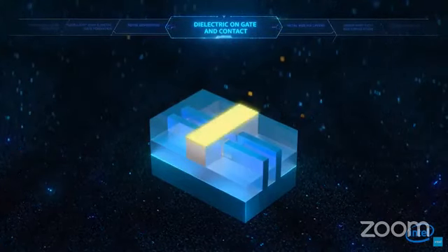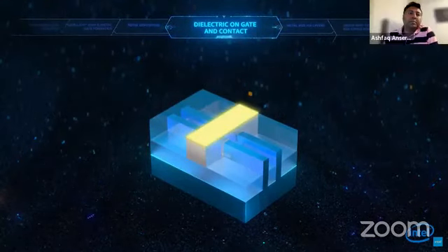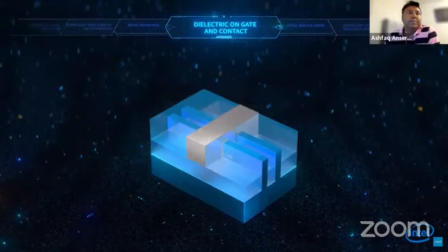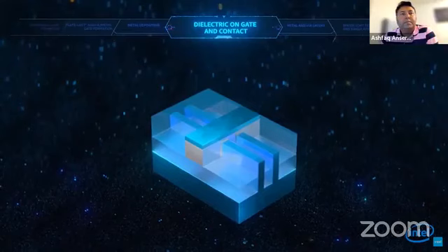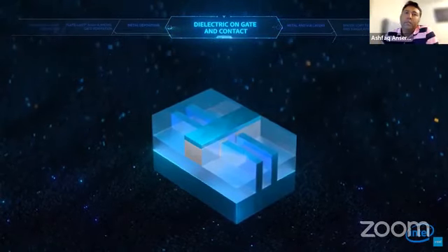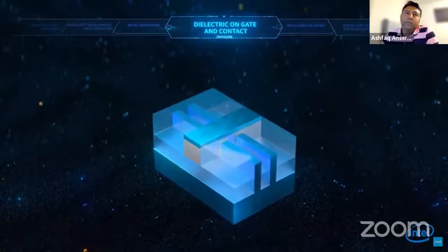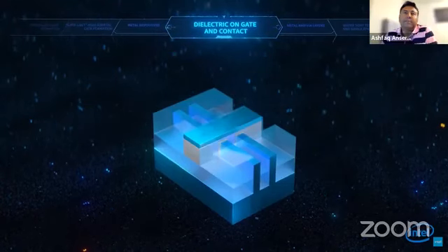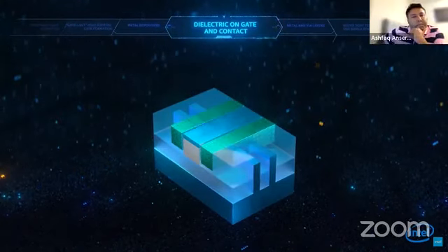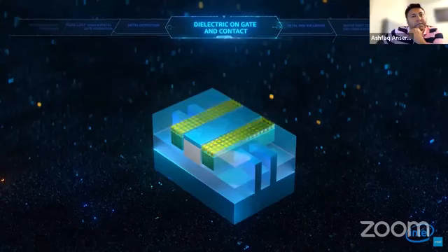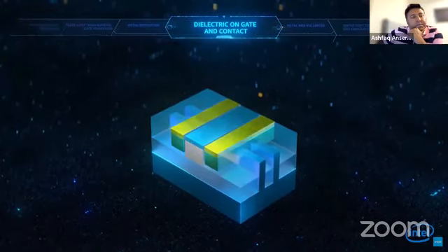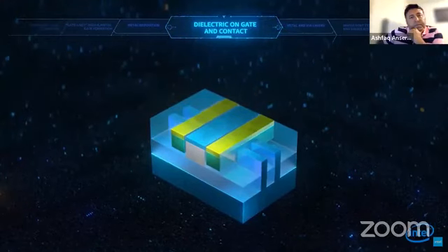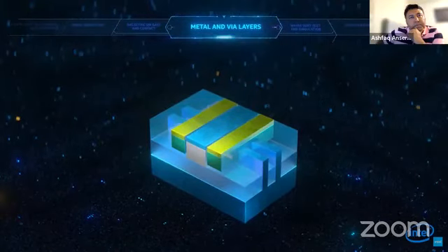Another invention moves the transistor contact directly over the active gate. To accomplish this, the gate material is recessed and then filled with insulating dielectric material to prevent the creation of a short circuit. Next, the dielectric near the gate is etched, filled with metal, recessed, and capped to allow a novel self-aligning process that enables high-density contact geometries.